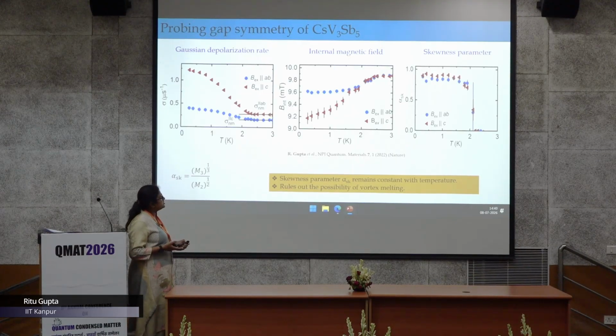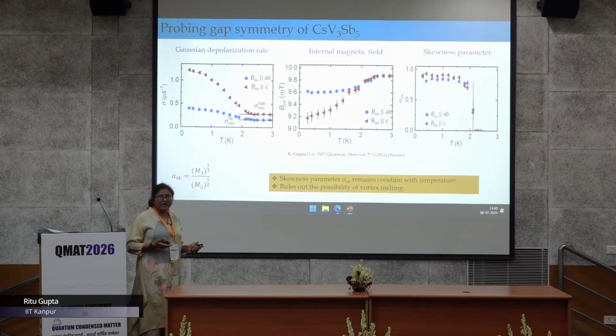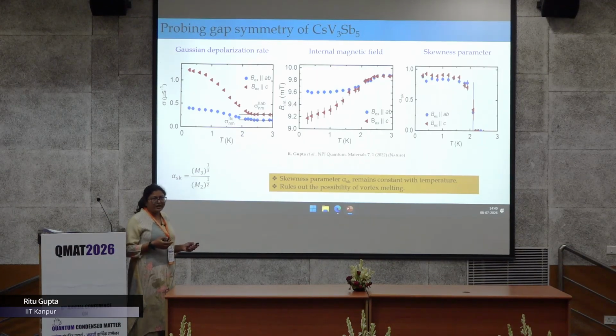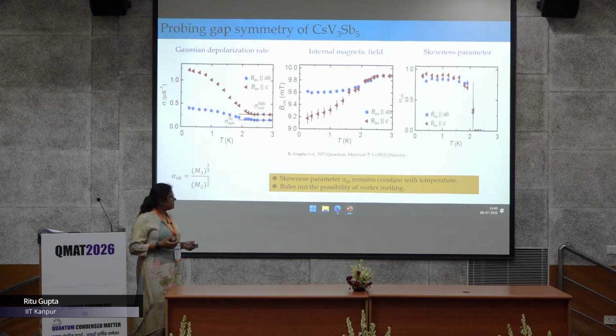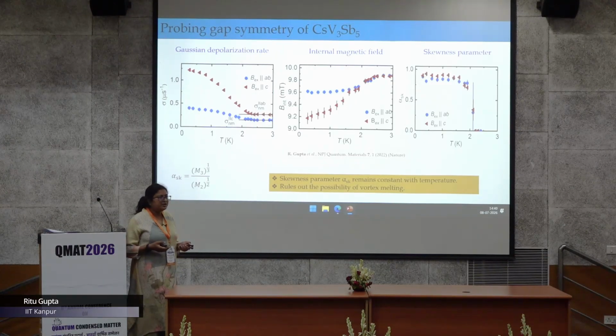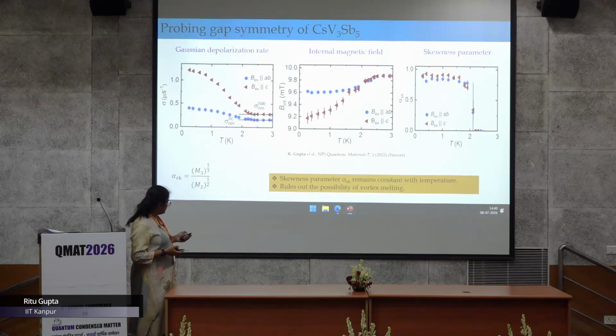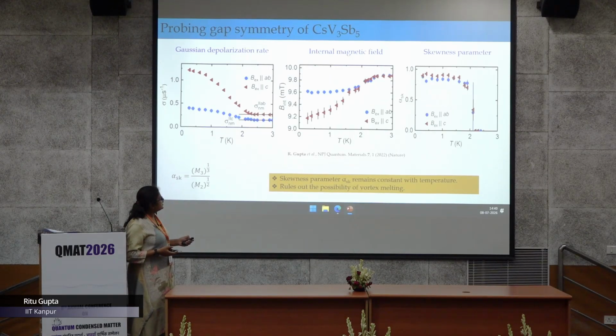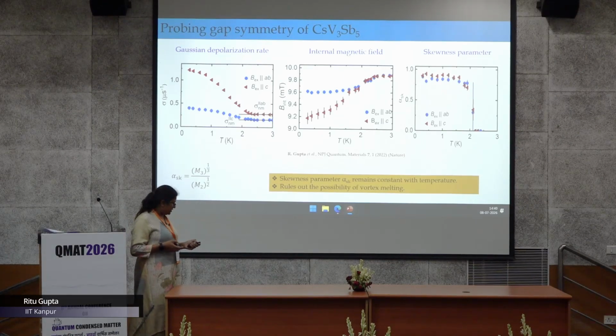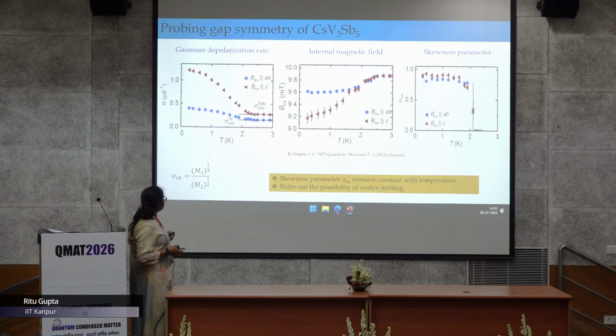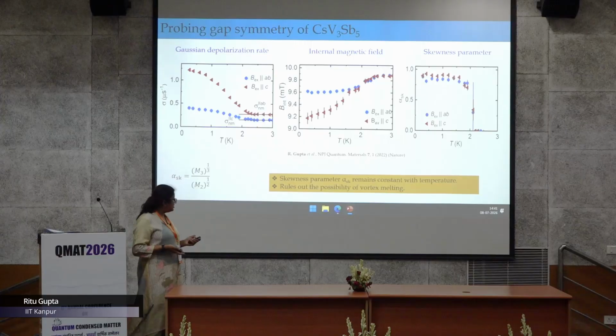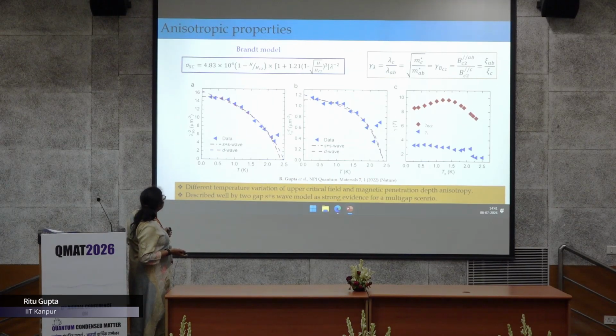If this ratio is close to 1, that means your vortex lattice is well aligned, well formed. But if you see a different value, that means there might be some vortex melting. So that kind of feature one can see. In our case, we see a constant value of the skewness parameter, which rules out the possibility of vortex melting. By subtracting this nuclear magnetic contribution, we are left with only the superconducting contribution, and this superconducting contribution is directly related to the inverse square magnetic penetration depth through this Brandt model.